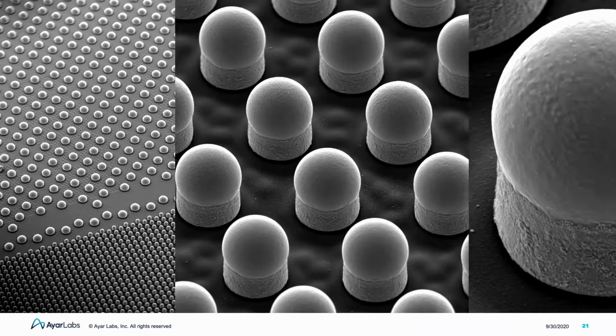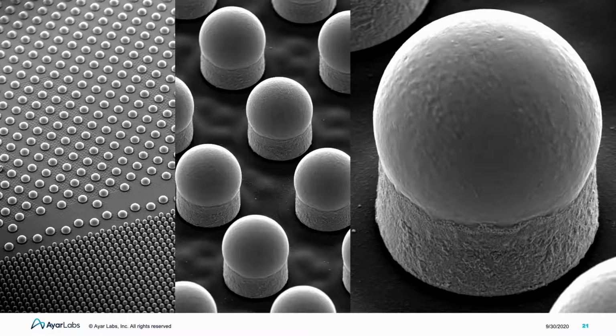Now let us switch to another component of the MCP, the copper pillar. Here we see copper pillars that have been fabricated on Ayar Labs Teraphy die. Note the mixed bump pitch design in the left image, the 55 micron pitch copper pillar in the center image, and a zoomed in view of a single 30 micron diameter copper pillar on the right. These structures are integral to a 2.5D assembly, particularly given the high density requirements of advanced interconnects such as AIB.